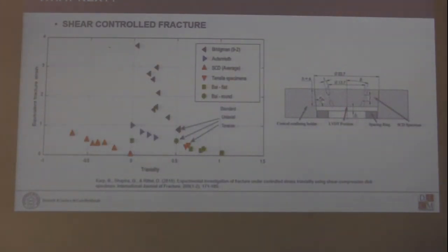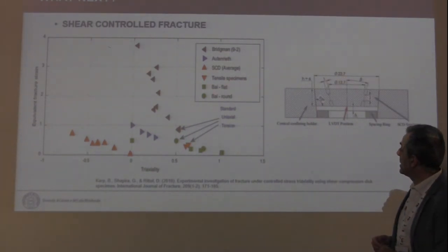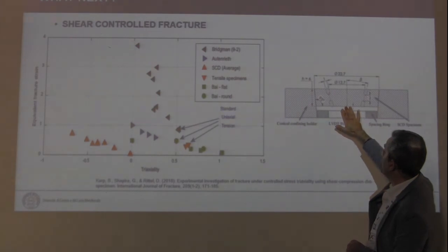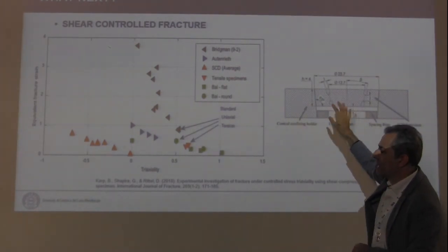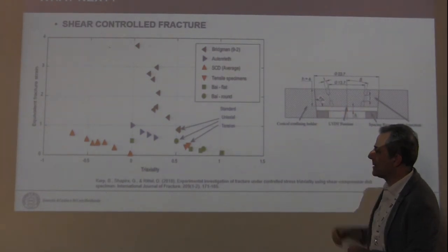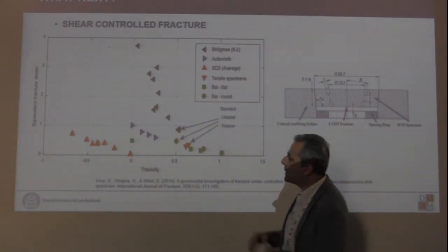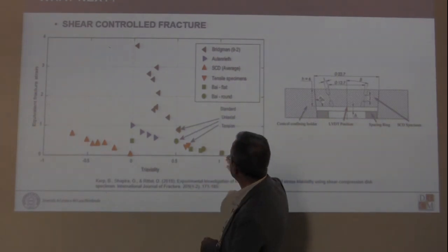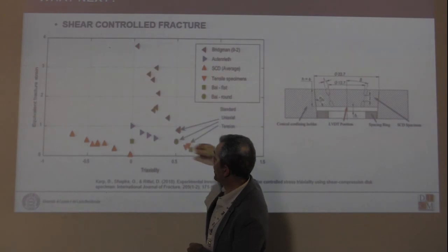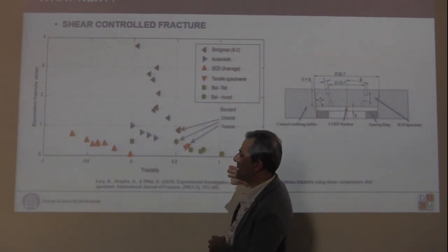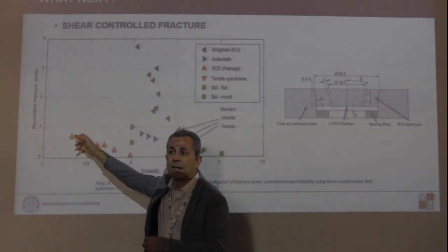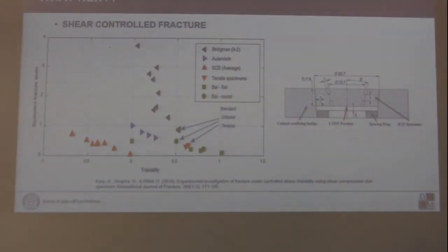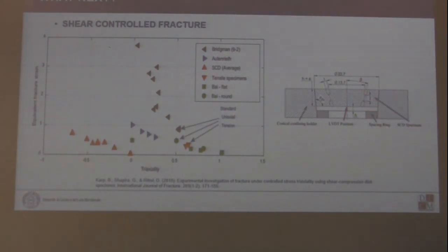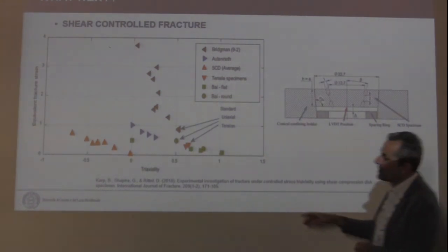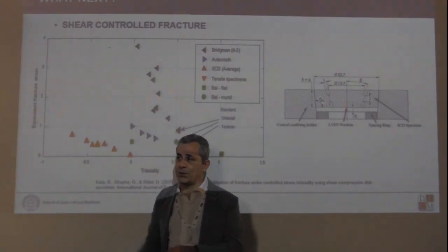A very interesting and conclusive result is provided by David Rittel at Technion in Israel. He developed a shear disk that overcomes many of the issues of the samples that Bao and Wierzbicki used in the past, and he found another very different behavior. For instance, this is the failure plot in the positive stress triaxiality regime. Then you have a drop, and then you have a straight line in the negative stress triaxiality regime. These are much more reliable results. So if this is the real case, then we need to revise our model in order to predict this behavior in this regime.